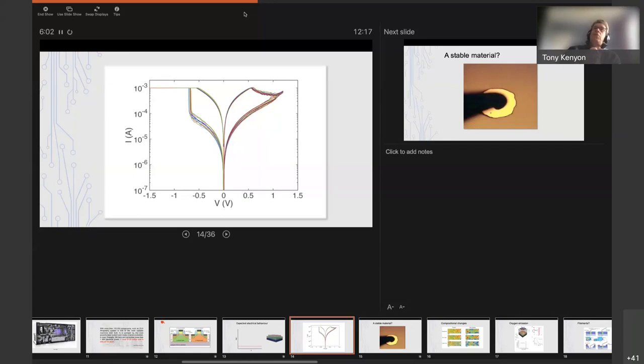The choice of electrodes is critical for a number of reasons. There are practical reasons, that some materials are fab friendly and others aren't. But beyond that, you could, for example, take a very simple system, where you had an oxide, let's say silicon oxide or hafnium oxide, and you just put the same metal top and bottom. A common metal that's used is titanium nitride. So you might have titanium nitride, oxide, titanium nitride. Well, in that case, the system is symmetrical whether you look at it top down or bottom up.